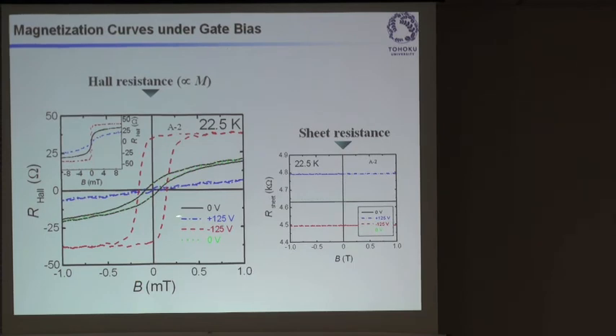But if you apply positive voltage, which corresponds to 1.5 megavolts per centimeter, depleting holes, we can completely destabilize the ferromagnetic phase at this temperature. And if you increase the hole concentration by applying negative voltage, we can see that our hysteresis becomes more square-like. And if you go back to zero volts, you see that you can get a virtually identical hysteresis curve to the one you started with.